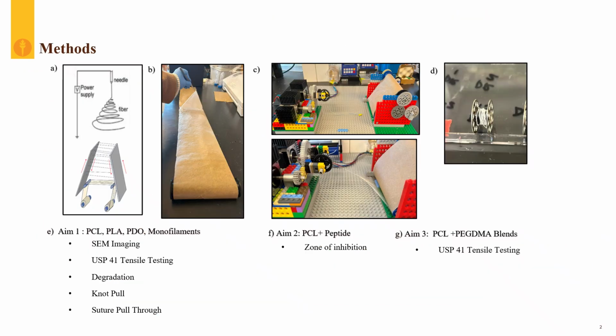So onto our methods, we made quite a few different electrospinning solutions with PCL, so just pure PCL, pure PLA, and then we had PCL and peptide or endolysin of varying concentrations, and then PCL and PEGDMA blends. We electrospun all of these onto our custom parallel track system, which allows for post-rolling capabilities and deposition of aligned fibers onto a roll-to-roll collector to allow us to create these long sheets of nanofibers, as shown in letter B.